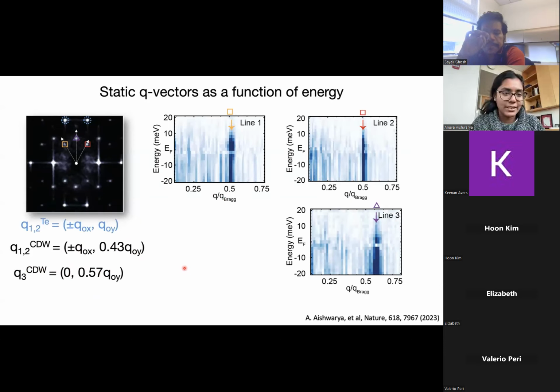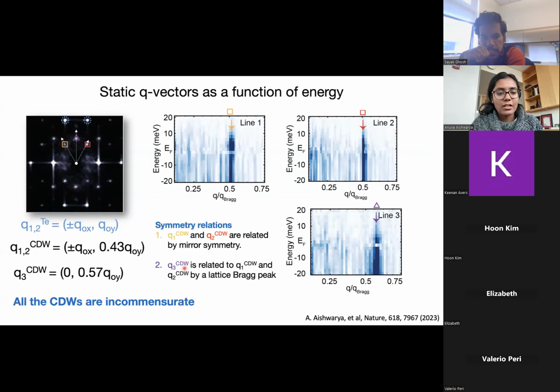lattice distance. So some of the symmetry relations between the CDW, and this will be important for the later part of the talk: the yellow one, let's call it Q1, is related to the red by mirror symmetry, and Q3, which is the purple one, is related to both of them through a Bragg peak.